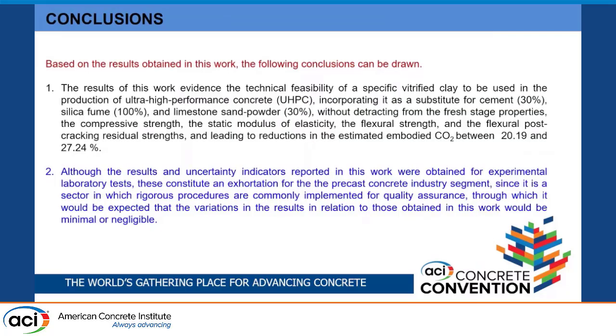So in conclusion, the results of this work evidenced the technical feasibility of a specific vitrified clay to be used in the production of ultra-high performance concrete, with the substitution of 30% of cement, 100% of silica fume, and 30% of limestone powder, without detracting from the properties in fresh and hardened stage, and also with an important reduction of the embodied CO2. Okay, although the results and uncertainty indicators reported in this work were obtained from experimental laboratory tests, these constitute an exhortation for the precast concrete industry segment, since it is a sector in which rigorous procedures are commonly implemented for quality assurance, through which it is expected that the variation in the results in relation to those obtained in this work will be minimal or negligible.